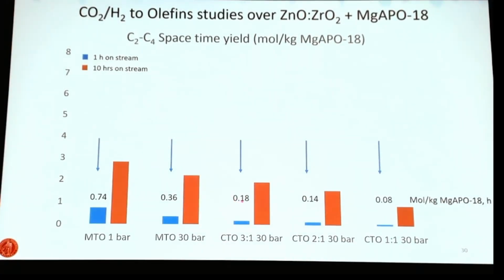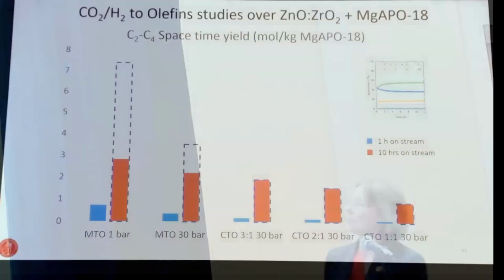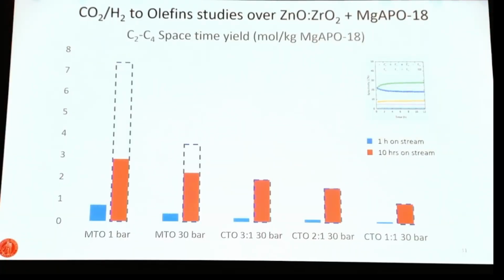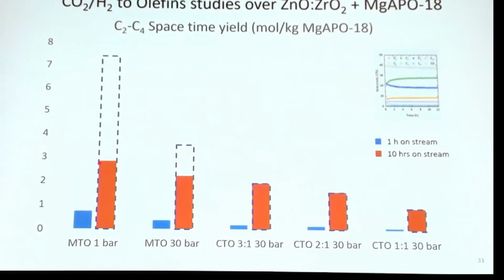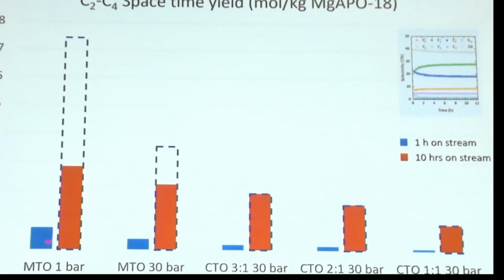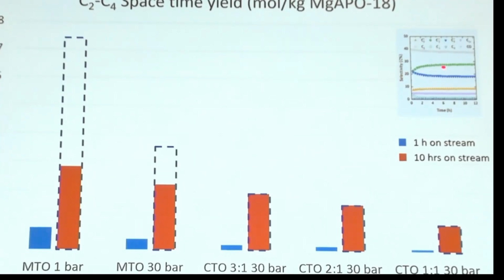But then we also see that if we have the same amount of zirconia and we increase the amount of magnesium AlPO-18, the turnover rate is decreasing, because the activity stays stable with an increasing amount of AlPO-18. On the other hand, just like what we saw from literature, the MTO catalyst under those conditions is deactivating. So the expected space-time yield will be up here. After 10 hours for this catalyst, it is much lower, same at high pressure, whereas it is maintained during the tandem conditions. And after 10 hours the performance is stabilizing, so we can expect that this is stable for a long time.